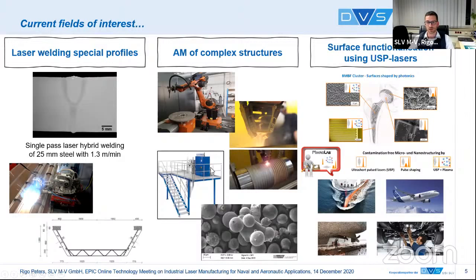In the middle, you see the additive manufacturing of complex structures, which is a fast-growing field in our house. Starting from large non-standard systems, where we can handle up to 6 by 3 by 2 meters in printing volume. We are developing for this because we usually use laser powers of more than 10 kilowatts, sometimes also 30 kilowatts. As you cannot buy so many optics for this, we had to develop our own optics and cladding nozzles. And we are doing this as a service also.